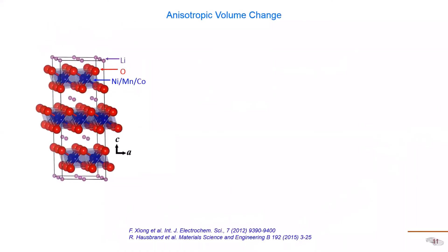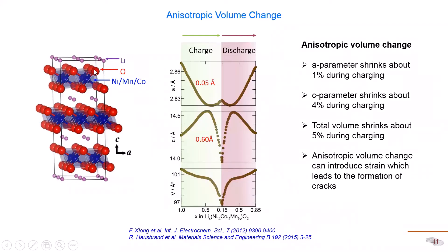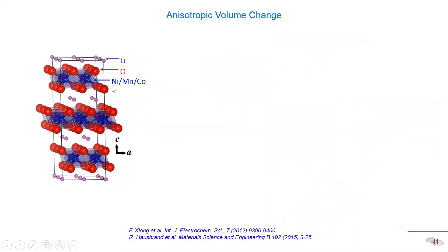Here I give an example of a material we are developing — layered oxides, which are actually quite old materials. Transition metals occupy the octahedral sites, oxygens form on the corners, and lithium ions intercalate. Today, people are trying to increase the nickel content and reduce the cobalt content because nickel-rich materials provide higher energy density and cobalt is very expensive and toxic. So nickel-rich is the way to go.